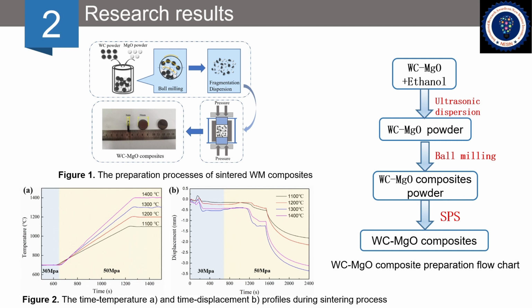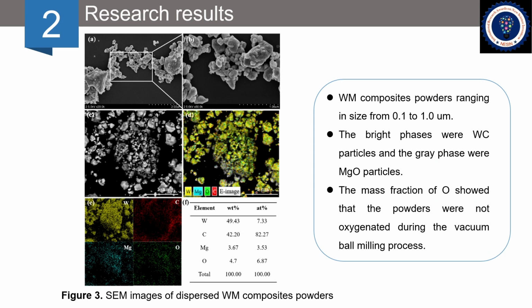SPS was used to prepare the compact WM composites with high vacuum conditions in the temperature range of 1100 degrees to 1400 degrees and the pressure ranging from 30 to 50 megapascal. Figure 3 was the pattern of the as-milled WM composite powders, from Figure 3A and Figure 3B. WM composite powders ranging in size from 0.1 to 1 micrometer mostly showed irregular polygonal shapes and good surface integrity. It indicated that the tungsten carbide particles and magnesium oxide particles were obviously refined after 50 hours of ball milling.